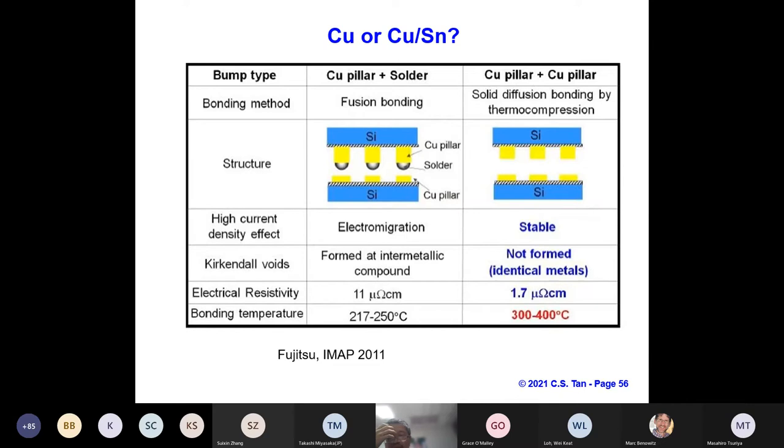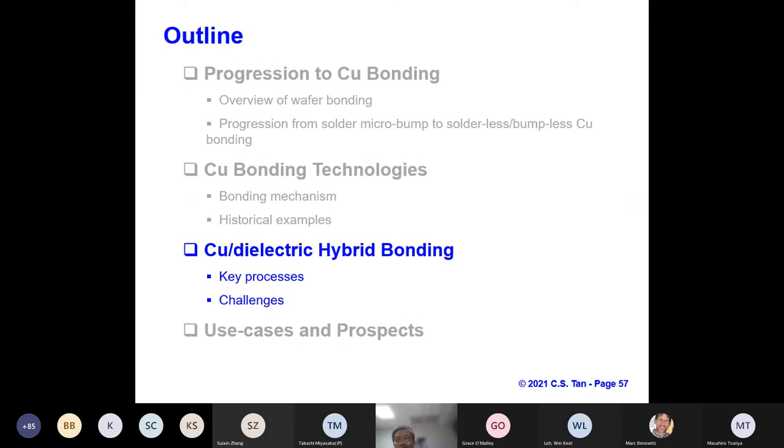The issue that you have to grapple with and solve is the surface oxidation, so that the bonding temperature can be lowered. I also reminded you earlier that the bonding throughput in the present day is still low. If you can think about how to improve the bonding throughput, that will be very helpful. The copper nitride approach that I showed you earlier is formulated in order to solve these bonding throughput issues. So that is the historical view on where we came from.